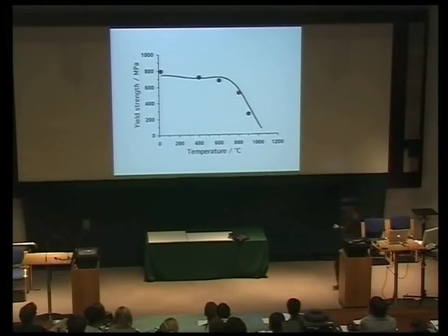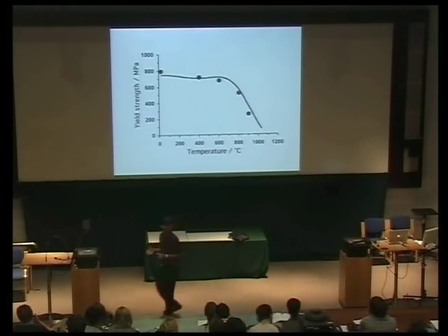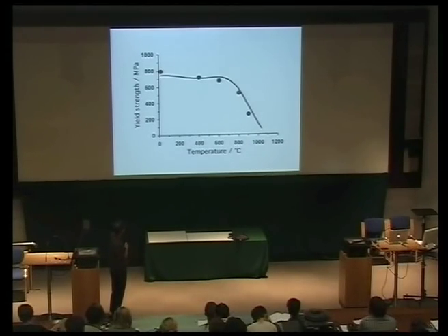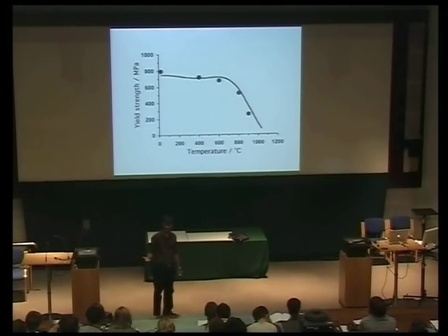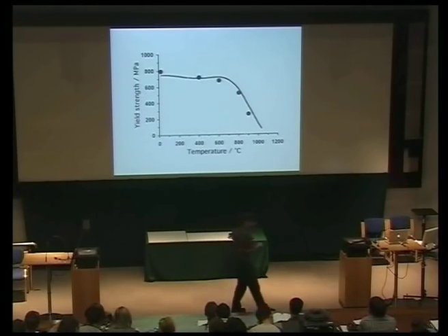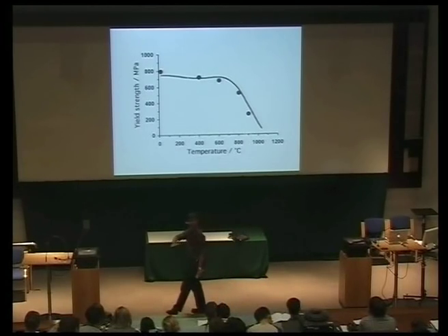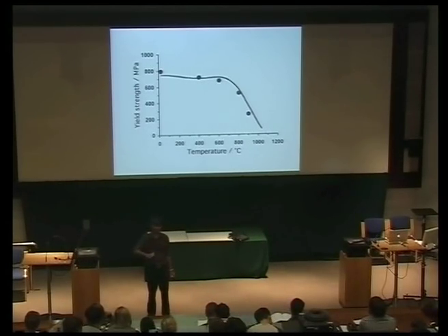So I was mentioning that there was a lot of work done on creating a 100% gamma prime alloy. We remove the matrix altogether, and the reason is that its strength is maintained as you go to high temperatures. Normally the strength decreases as you increase the temperature. Here the strength is actually being maintained or increases in some cases as you raise the temperature. And the reason is, although the normal slip occurs on the 111 planes of gamma prime, as you raise the temperature, the fault energy on the 100 plane decreases.